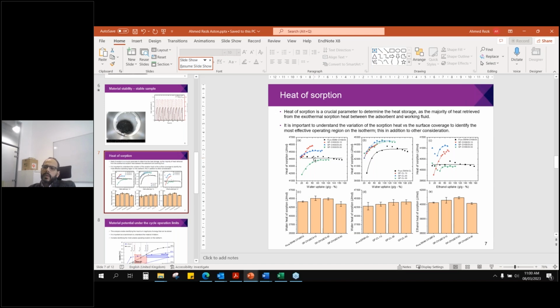Because later we're going to put this cycle on the isotherm, and if the cycle occurs in the high heat of absorption region, then we have a good combination. Otherwise, we need to think about how to utilize this material better. Although actually the main sorbent material here is the salt itself, not the host matrix. The host matrix was carbon and doesn't absorb or dissolve water vapor. But the dispersion of the salt within the host matrix had an effect. So for example, here at high surface coverage, we have higher heat of absorption, which makes sense.